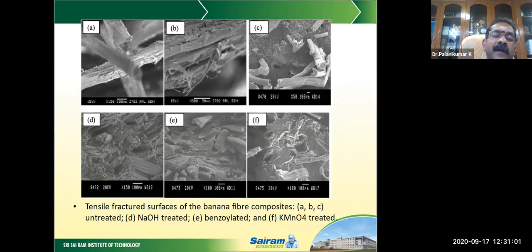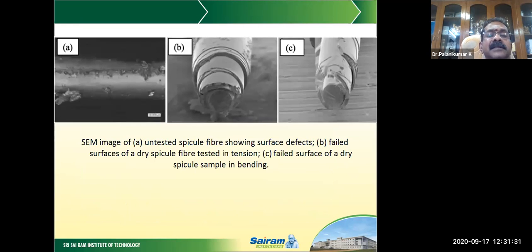This is the tensile fractured surface of the banana fiber composite. A, B, C for untreated fiber, and D for NaOH treated, benzoylated treated, and KMnO4 treated. So the different treatments give improvement in the properties. So the burrs and other things are removed so that we are able to get a smooth surface. SEM image of untested spicule fiber showing surface defects. B, failed surface of a dry spicule fiber tested in tension. And C is the failed surface of a dry spicule sample in bending.